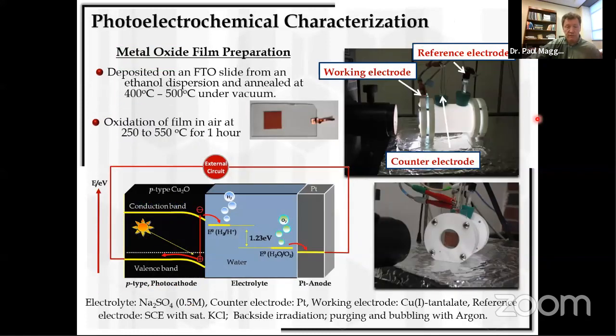We took each of these because when we suspended them in solution, we didn't see much activity. We took these as particles, and you can anneal them on FTO slides and create photoelectrodes from them. And so this is what we did. So we can apply potential and see if, upon irradiation, we have N-type or P-type semiconducting behavior, and if photocurrents are very high.